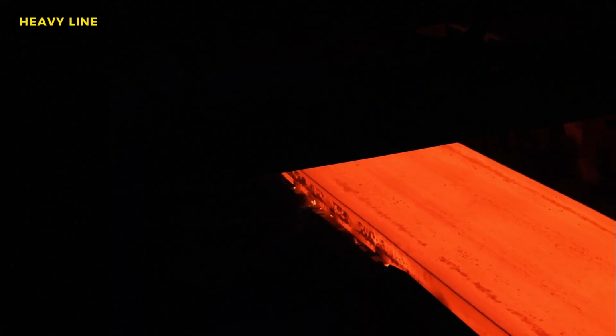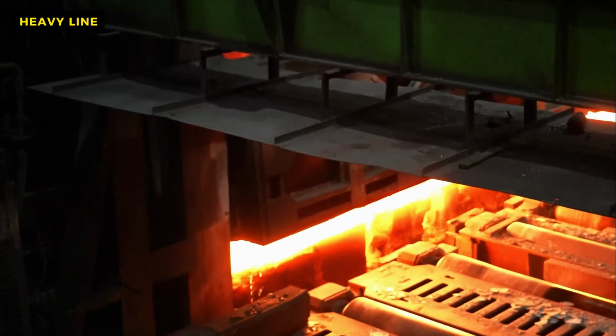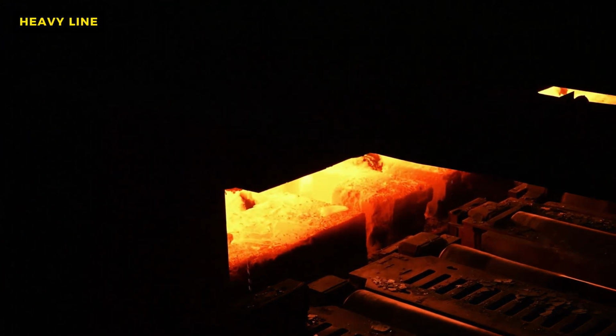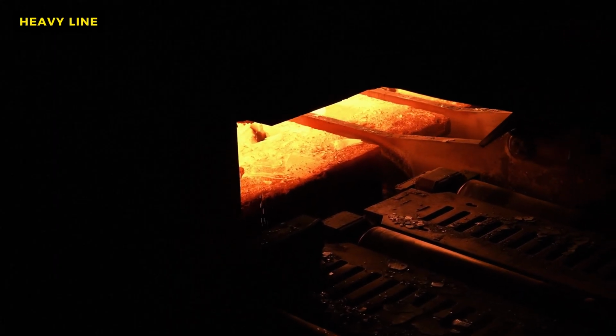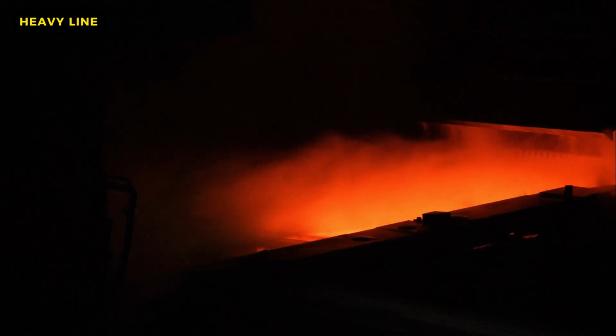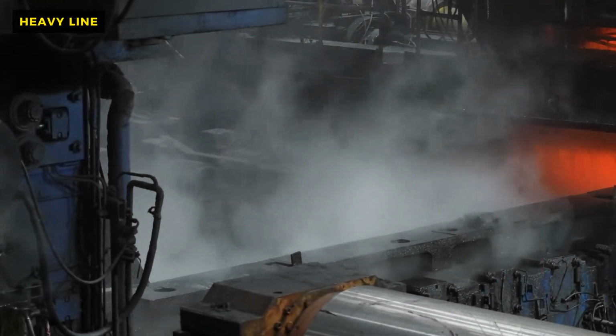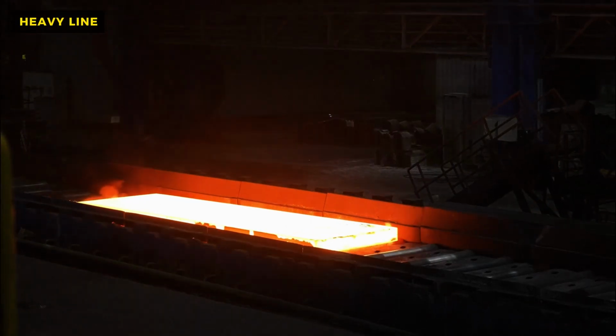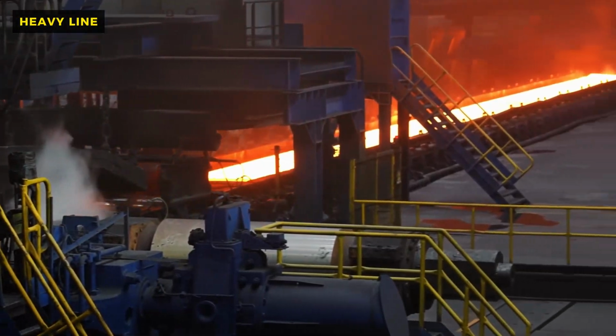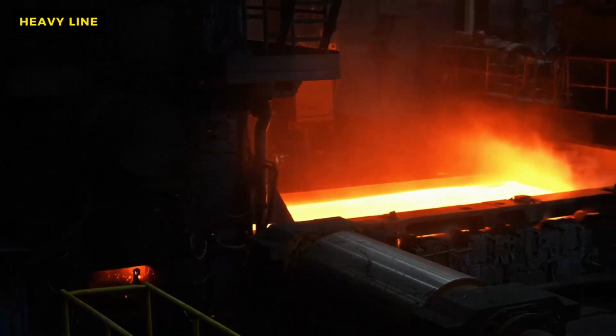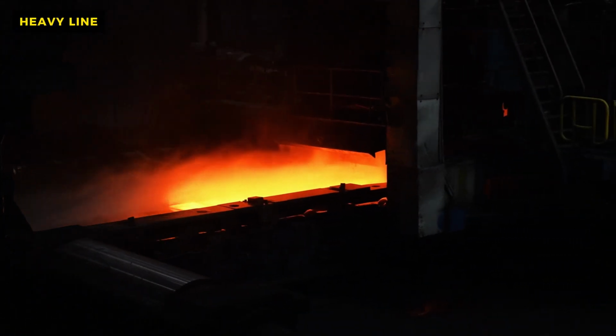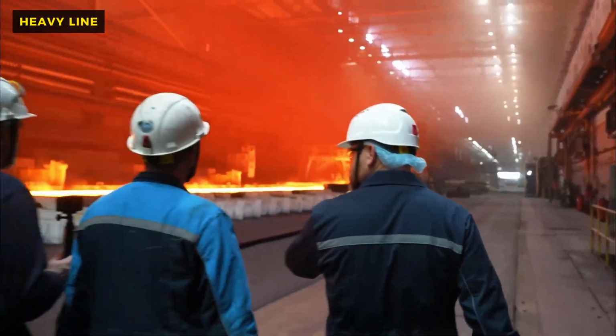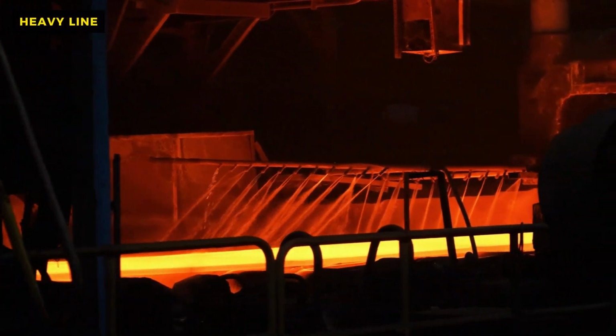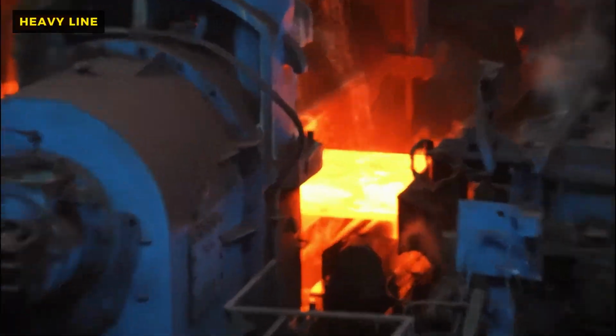The coke ovens are narrow, deep chambers lined with silica brick arranged in long rows like books on a shelf. Coal is dropped into these chambers and heated to 1,100 degrees Celsius for 18 hours. Because there is no oxygen inside the chamber, the coal does not burn. Instead, it sweats. The volatile gases, the tars, and the oils are driven off, captured, and piped away to be refined into chemicals, leaving behind a hard, porous gray rock that is almost pure carbon. This is coke. It is incredibly strong, capable of bearing the weight of a skyscraper of ore, and it burns with a clean, intense heat.